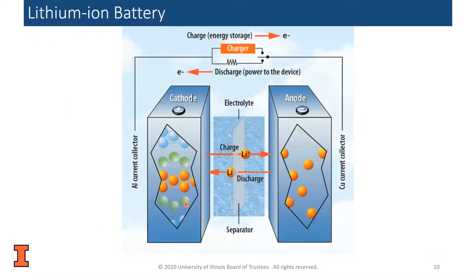And so they consist of a lithium metal oxide at the cathode. And during the charging cycle, the lithium drops off an electron and then moves over to the anode where it intercalates between layers of graphite. And there it picks up another electron. And then during the discharge cycle, the lithium drops off that electron, moves back to the cathode, intercalates between layers of oxygen, where it picks that electron back up again. And it's this ability to shuttle the electrons back and forth that allows this device to store energy and deliver it as a battery. So what does the battery look like inside?